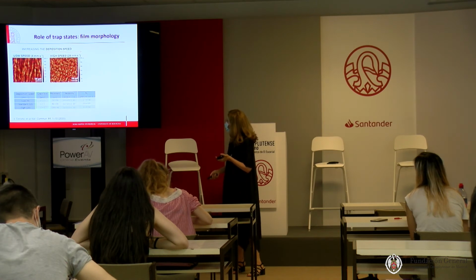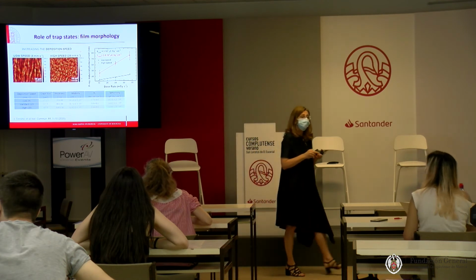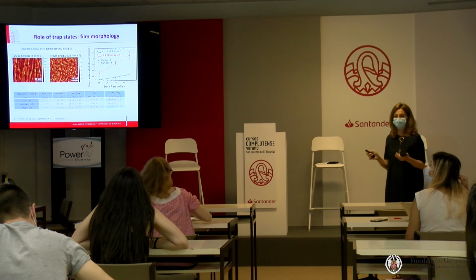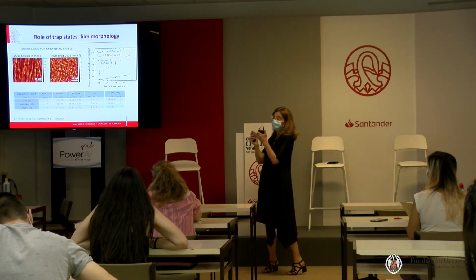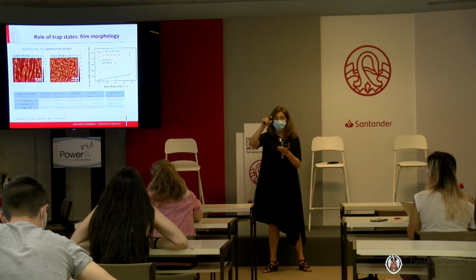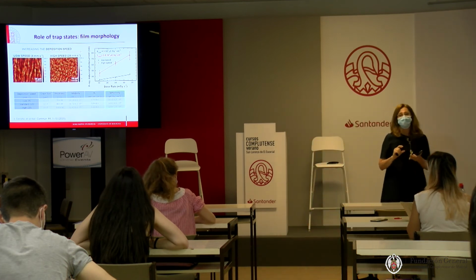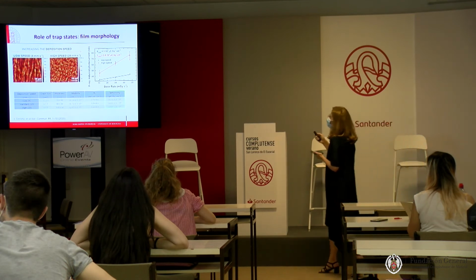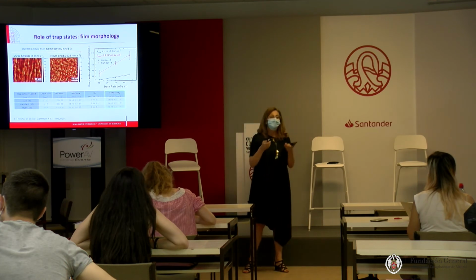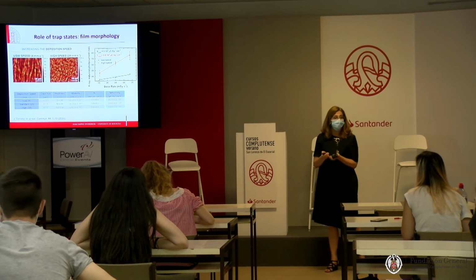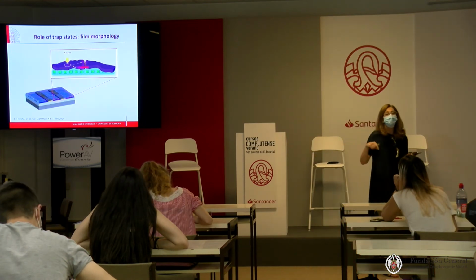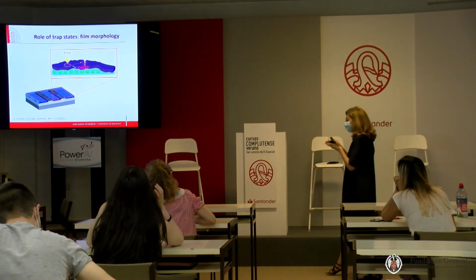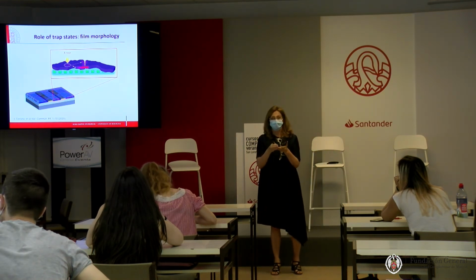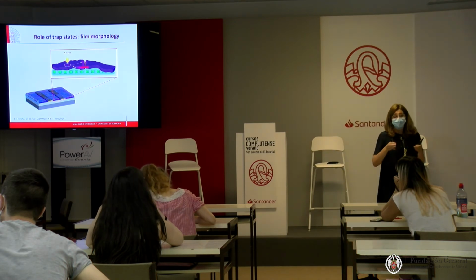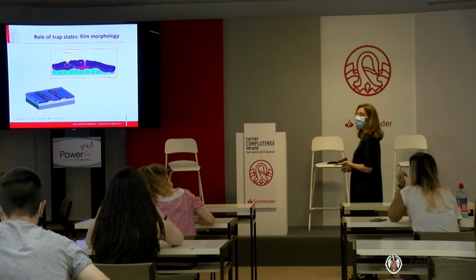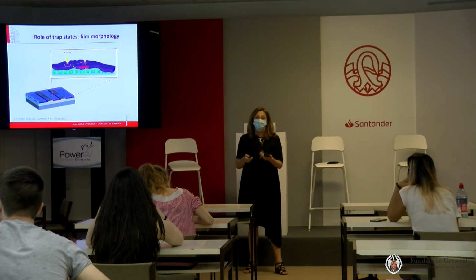If we reduce the grain size, look at the photocurrent. The photocurrent increases, given everything else identical. Why is it so? And the photocurrent not only increases, but the slope increases. And we know that the slope of the photocurrent versus the dose rate is the sensitivity, which is a very important figure of merit of our detection. So why is this interesting? Because we understand and we validate the role of traps. Because if we have smaller grain, what happens is that we have more interface between one grain and the other, and it is at the interfaces that the defects are created and are active. So if we have smaller grains, we have more defects, and that is why the photoconductive gain increases, and we have a higher sensitivity.